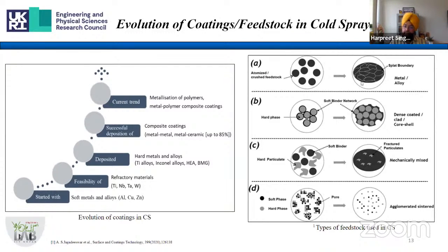And in terms of feedstock, we have these atomized feedstocks being deposited, having splat boundary, of course, up to this nice coating, standalone powders, maybe metal alloys. But then in case of hard phase, we have these core shell kind of powders where we have soft binder on it, and then we can deposit them. But then there's a lot of composite coatings work also, where we have softer binder and these reinforced particles, which can be mechanically mixed and then deposited and so on. And there's another soft phase and hard phase kind of fused, what they call fused and sintered, and then when they are deposited, they can disintegrate and so on.